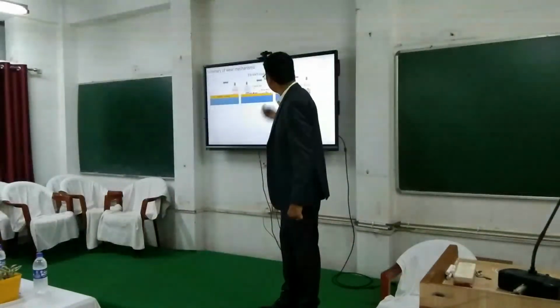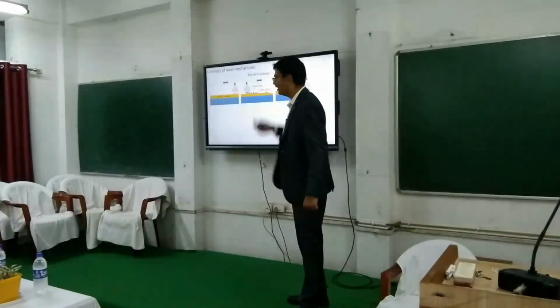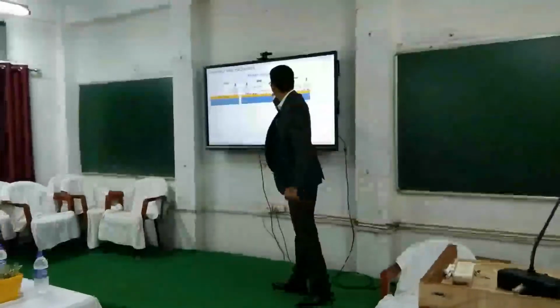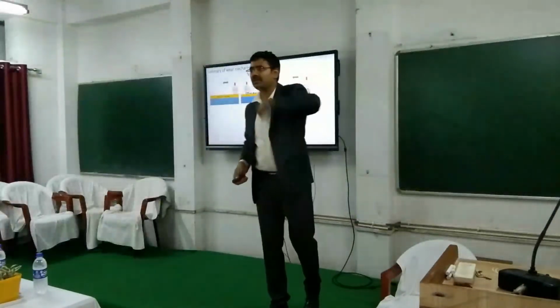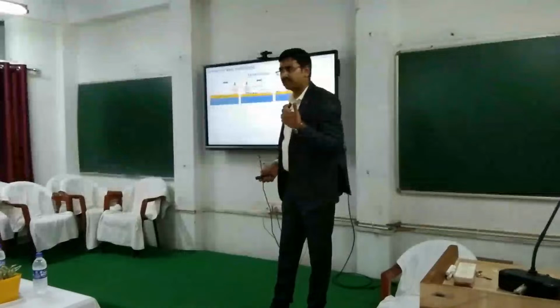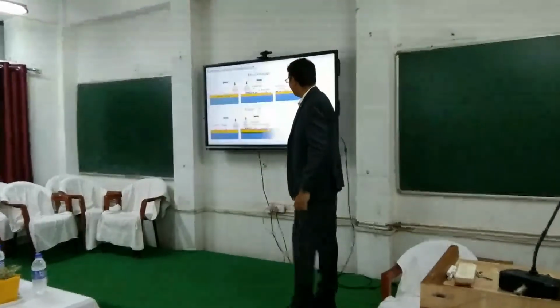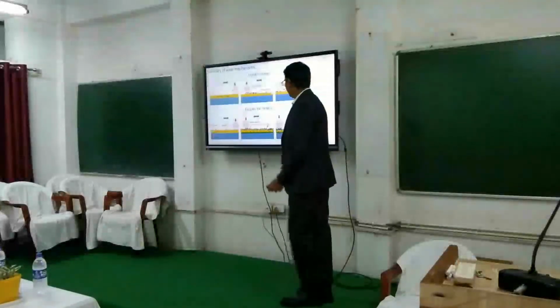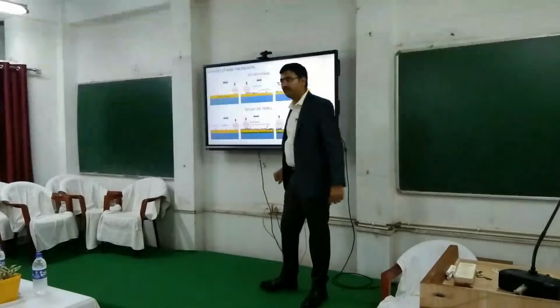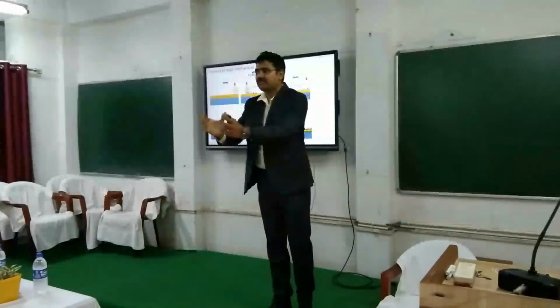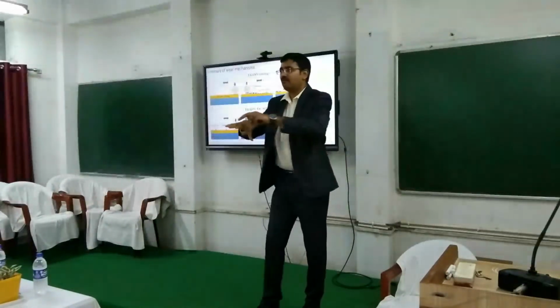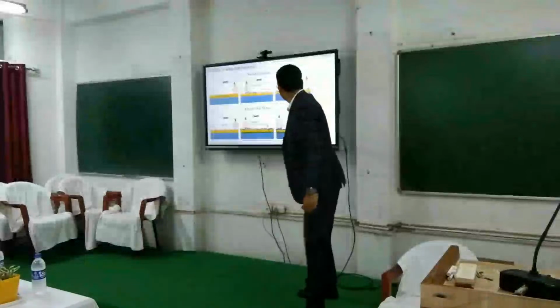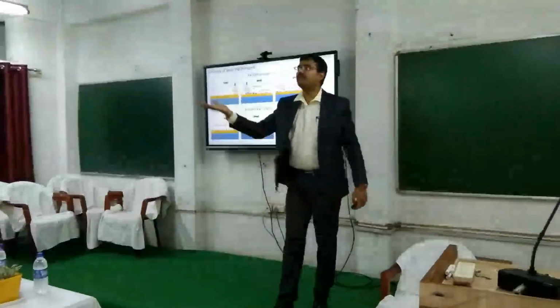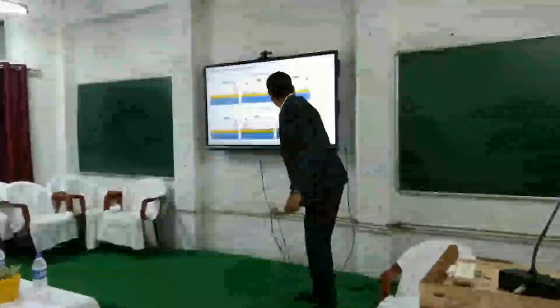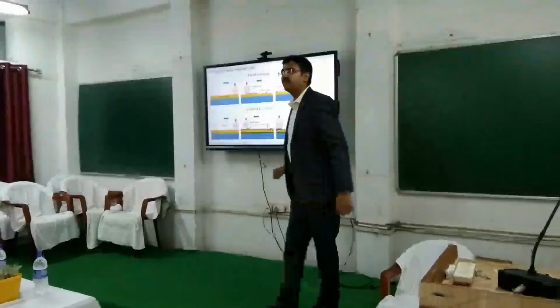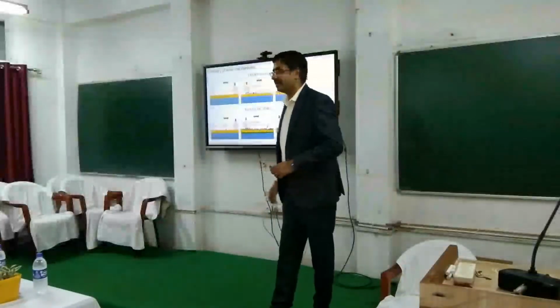So last, the summary of wear mechanisms. In titanium 64, we have continuous debris formation, and these debris are flowing as the test progresses. That's why you are getting abrasive wear. In case of metal matrix composites, although initially some debris are getting formed, they are getting smeared and sintered around these carbide particles, forming protective layers, and that layer is giving you some kind of load support.